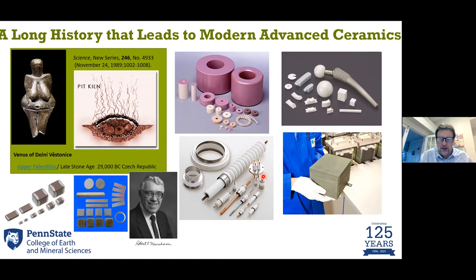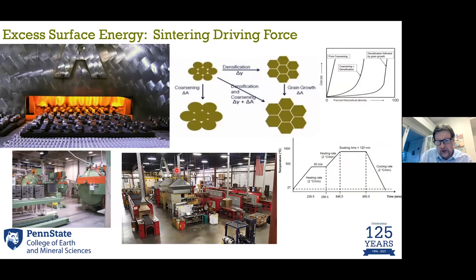They use furnaces in a factory floor like these different examples here all over, and they generate enormous amounts of waste heat in the densification process of these ceramics. Remember taking these powders and then driving them into a dense monolithic sample, going from about 40% dense to about 98% dense. And in doing so, being driven by the thermodynamic process of minimizing surface area. And the sort of temperature profiles that these furnaces take is processes that then remove organics, say at 500 degrees, and then driving a temperature up to temperatures such as 1,000 to 1,600 degrees Celsius.